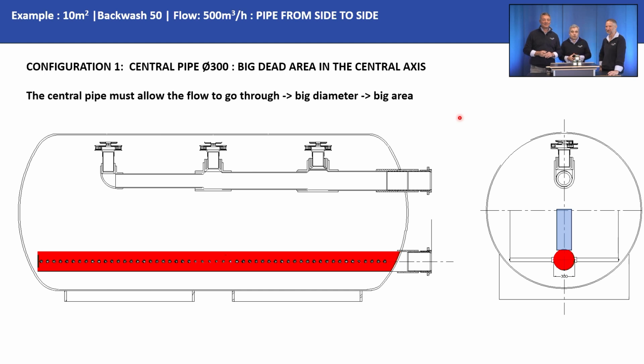Good. Well, we saw before that the horizontal filters, due to the geometry, have dead areas in many places, but also small changes in the design can make it better. So we have the classic configuration. We have an example of a 10 square meter filter with a backwash of 50. So we will have a flow of 500. This means that we will need to install a pipe of around 300 in the middle, from side to side, and this means that we will have a dead area of 300 in the middle. So that's the standard design of most horizontal filters. Classic design: big pipe below, big pipe above. Yes, we will have long laterals, but just take that apart. We will have a minimum dead area of 300 in the middle.